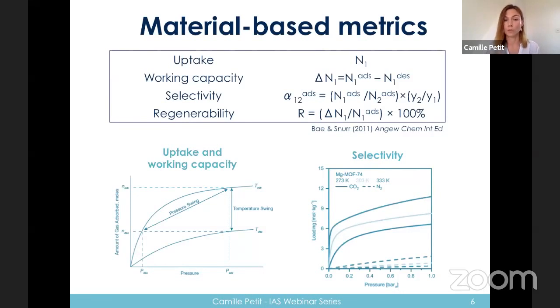We have then also to consider the selectivity. So when you want to separate 2 species, there is one that you hope will be adsorbed preferentially versus the other. That will characterize the selectivity. So if you look at the graph at the bottom right here, you see that the thick solid lines are for CO2 versus the dotted lines here are for nitrogen. And so we have a preference towards CO2 adsorption, and so from that we can start calculating what is called the selectivity. And finally, we have the regenerability, which characterizes how much of the adsorbed amount can be recovered upon the cycle of adsorption and desorption.